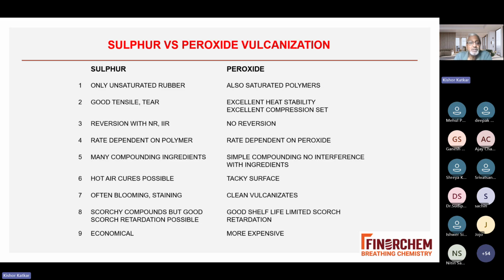Sulfur gives a reversion in case of natural rubber and polyisoprene. Peroxide, no reversion. Cure rate depends on the polymer. It depends on the peroxide, type of peroxide, quantity of peroxide. And also activator. There is a peroxide activator also used to reduce the peroxide consumption. Many compound ingredients in sulfur: you require zinc oxide, stearic acid, 2-3 accelerators, sulfur, retarder, etc. In peroxide, it's a simple compounding, no interference with ingredients, maybe only peroxide plus activator.